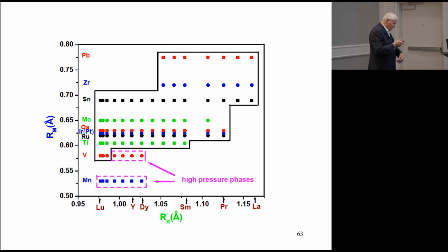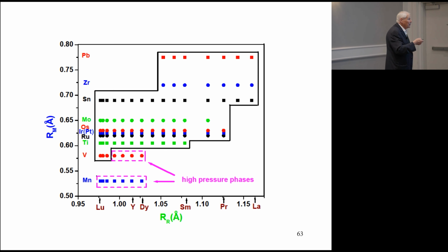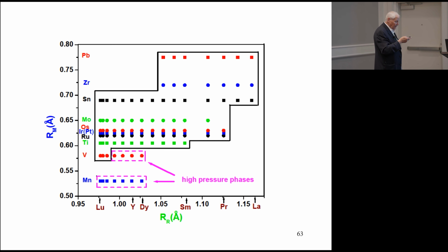Now, here's a structure field map of pyrochlore oxides. You can see, mainly looking at the A-site ions, they are mainly lanthanides. B-site ions can be any of these species here. Some of them are stable only under high pressure conditions, and there are many others that are not included in this figure, which have been realized lately using high pressure techniques. But this is the sort of equivalent, if you like, to the Goldschmidt tolerance factor for perovskites. So completely in the spirit of studying the structure-property relationships across the series, we make the A-site ion a rare earth, and just cruise across the rare earth series to see what happens.